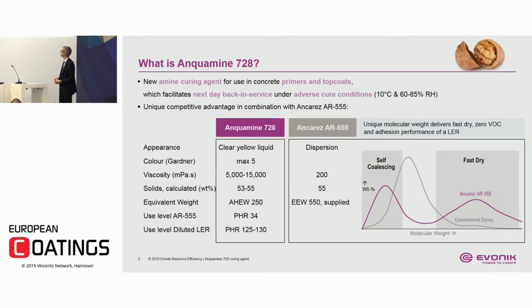The other thing is that this is a system designed for concrete coatings, and that means that the concrete is a bit temperamental. Dry concrete is very nice, but it hardly is ever there. So concrete's always a bit damp. And in order to get a good adhesion to damp concrete, you need a good film formation at low temperature. And that's exactly what the 555 does for you.